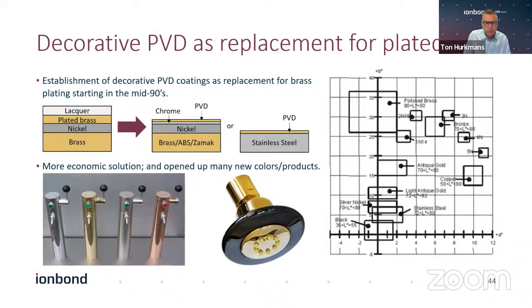Another example that's also already originating from the mid-90s in the decorative field, but that's not just for the looks, but also for wear resistance. But decorative PVD coatings have been replacing electroplated brass. And in the old days, a fixture for your bathroom was plated with nickel layers, nickel chromium layers actually, sometimes copper nickel chromium, but then there was a plated brass for the looks with a lacquer. This is all replaced now by PVD technology, zirconium nitride coating in this case, and the lacquer layer was also